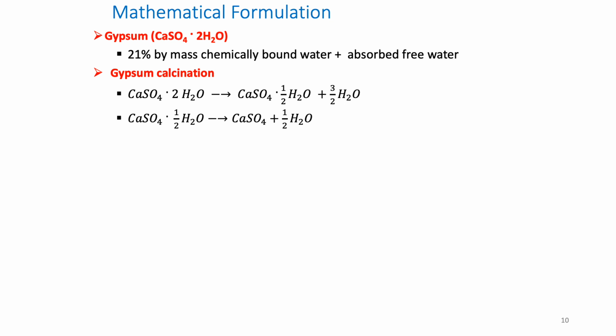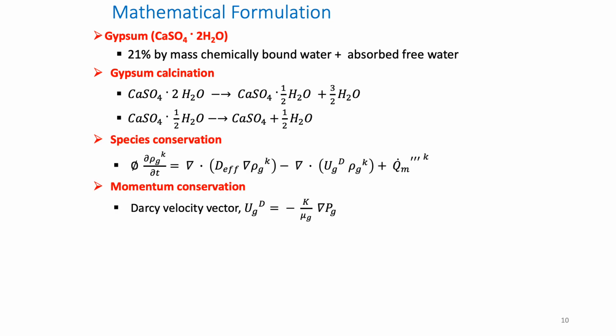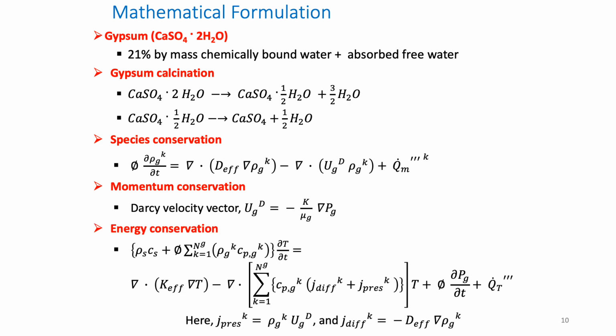Mathematical formulation: we assume gypsum board as a homogeneous porous material, and we looked at gypsum chemistry, which happens over 2 steps, and species conservation equations for both water vapor and air, and momentum conservation equation using Darcy velocity vector, and energy conservation equation that considers both the solid part, the water vapor and air, and effective conduction, the mass transfer because of both concentration gradients and pressure gradients, and also we consider the source term.